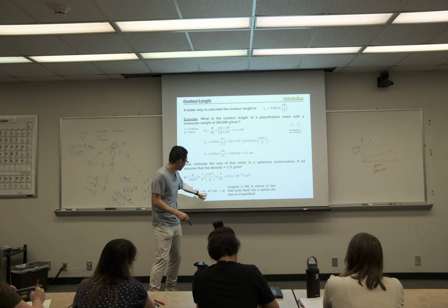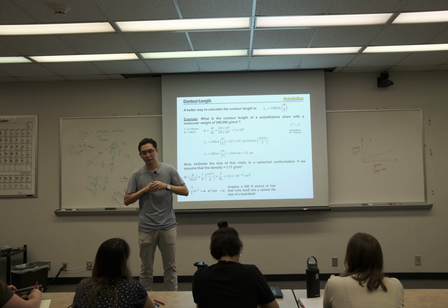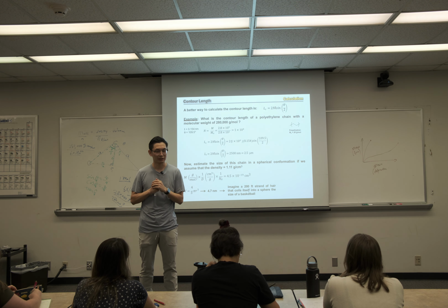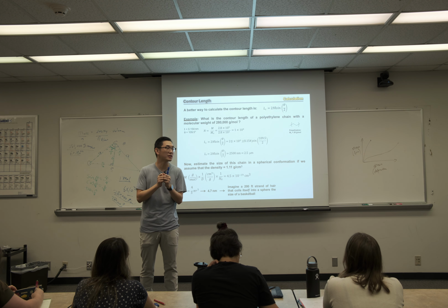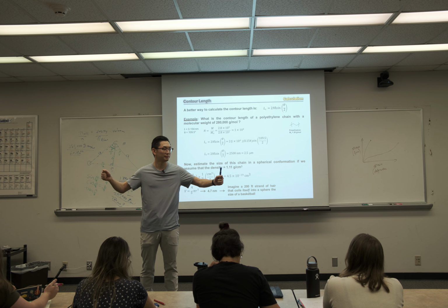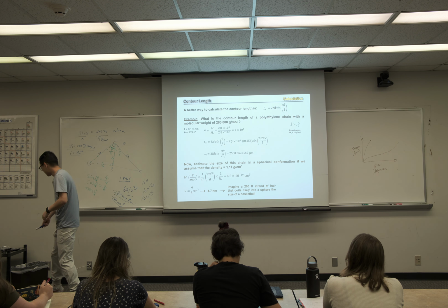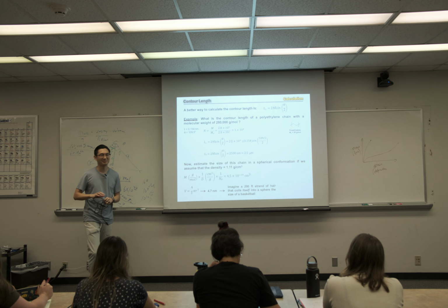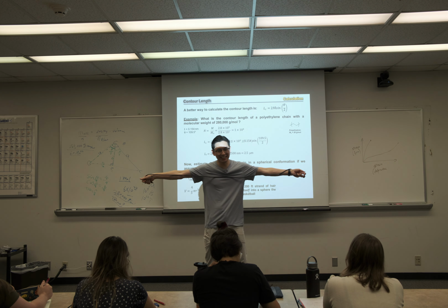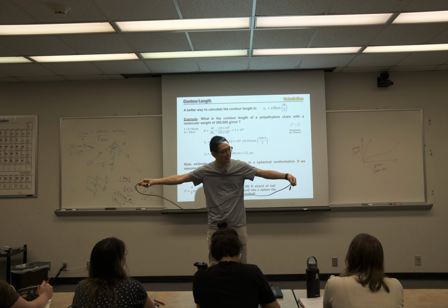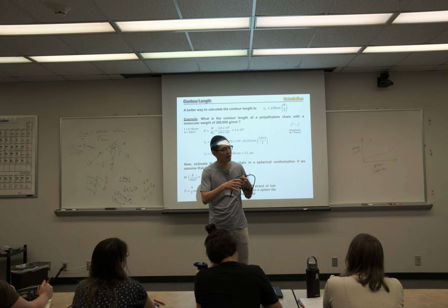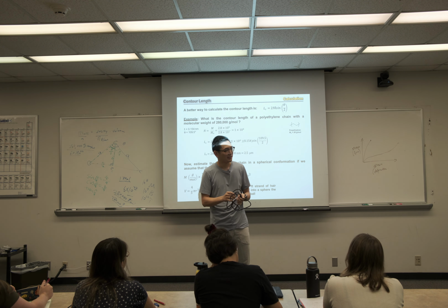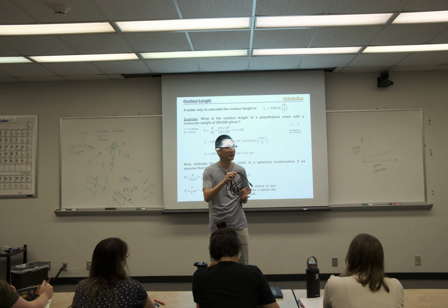If it's fully collapsed, it will go down to 4.7 nanometer. So that gives you some size idea of how big the polymer can go from conformation change. Let me do a demo. I like demos. So fully extended, when we fully pull it, it will be micron size, and if you dissolve it in solution, it will form a random coil.